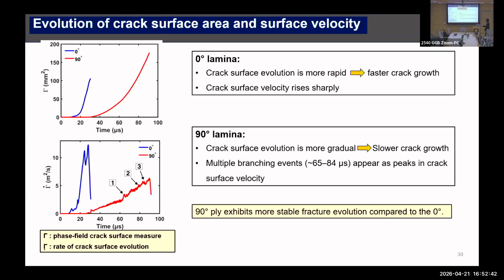Whereas in 90 degree, it's more stable, and these little spikes basically tell us every time we see another branching appearing. So we can actually track when the branchings are happening just by looking at this velocity profile.